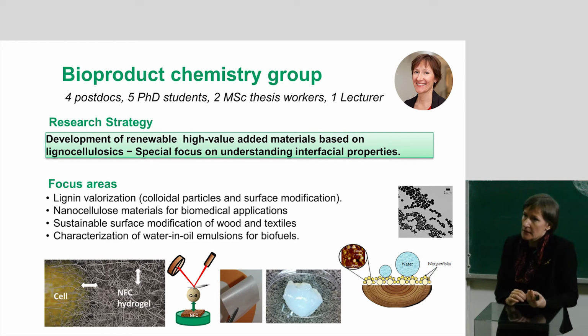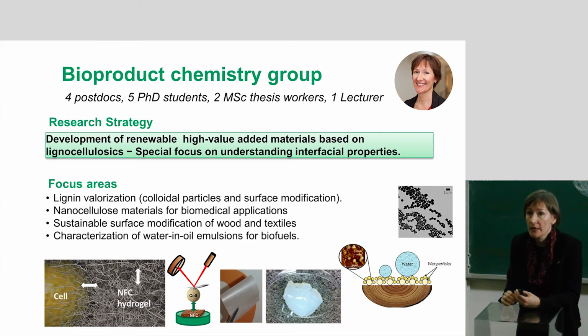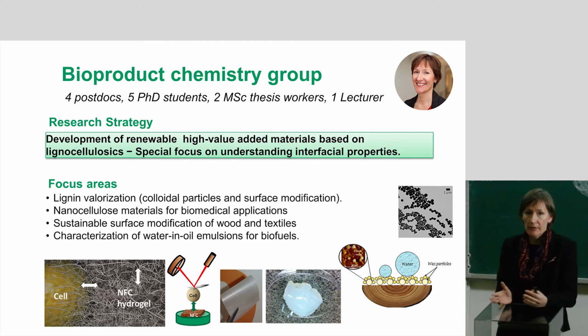And I tried to develop these materials by looking at the surface or modifying the surface. And why I do this is because you can really affect the material properties by just changing the surface. So by surface modification, you can decide whether a droplet of water will stay as a droplet or will spread on a surface. And more importantly, you can also affect the interactions, whether some fibers, in a composite, will have a good attraction to the matrix or not.